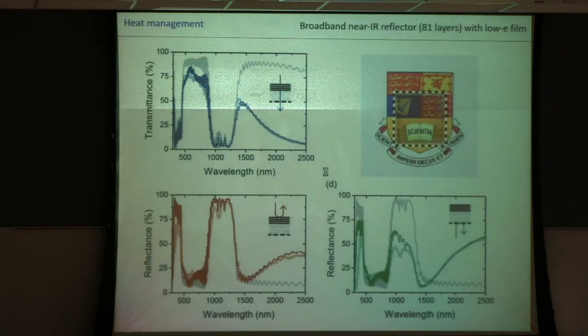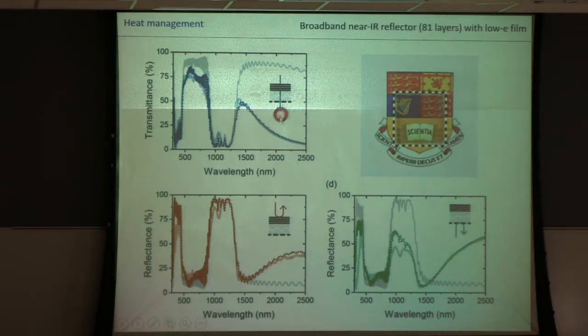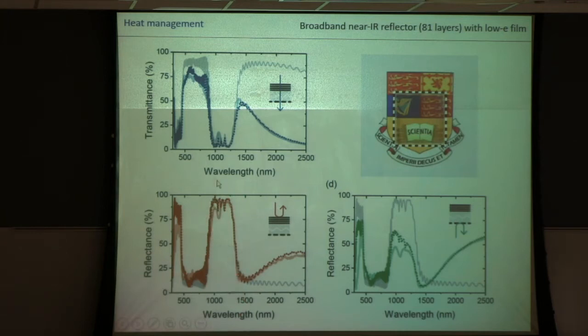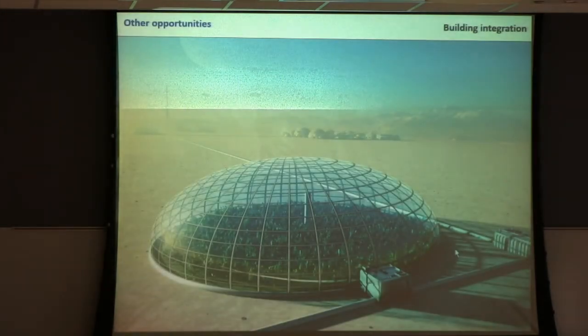And once we make that, these are now real mirrors in blue. You see we actually still get a pretty high transmittance in the visible. We lose some, and this is due to the oxide layer. And we get a high transmittance here in the mid-infrared regime. Afterwards, the low E glass will take care of it. In reflectance, you see we have massive reflectance when we come in from the outside. So that's what we want. We reflect the heat that the sun produces, while on the inside, we keep the black body irradiation in the house. So this should be really a perfect system for broadband chirped mirrors.